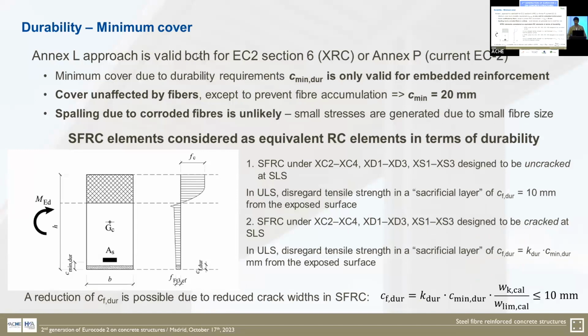And then in terms of durability, we have to say here that the use of steel fibers does not lead to a reduction of the durability response of the concrete. This durability is governed by the longitudinal and transversal steel reinforcement. But in any case, Annex L asks for a minimum cover of 20 millimeters to guarantee that there is no accumulation of fibers in the bottom or in the borders of the section, and also for the sake of safety, proposes that in ultimate limit state we do not take into account the contribution of tensile residual strength in these exposure classes, in case that no cracking is expected.